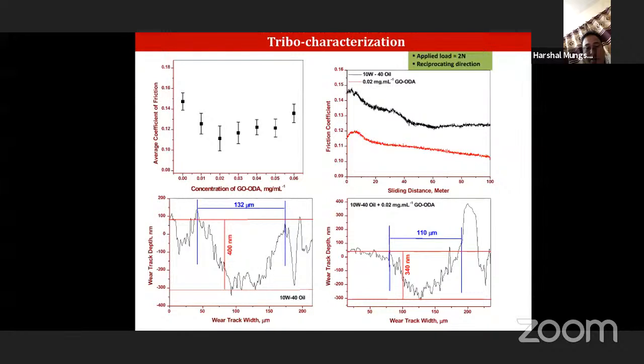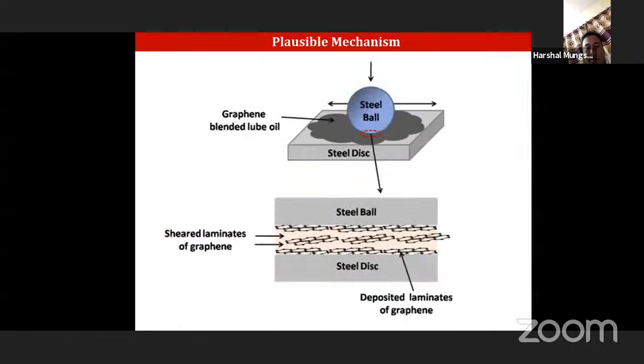Another graph shows the wear track depth. You can see in one example 400 nanometer, in another case 340 nanometer. That 340 nanometer depth is because of the application of this functionalized graphene material. We can reduce the wear track width and depth by using this material.